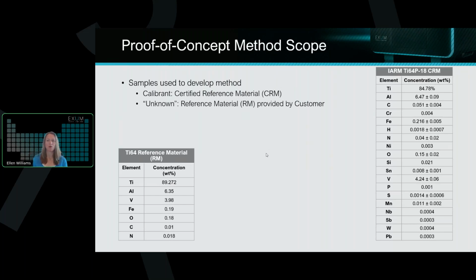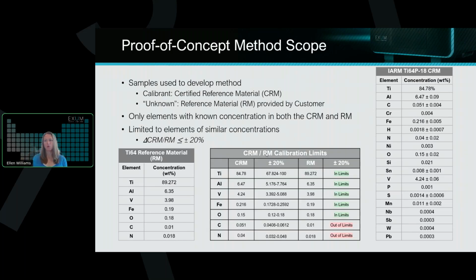So in this case, we have what you see on the left, which is a Ti-64 reference material we received from a customer that had sent this out to one lab and gotten one number for the elements of interest that you see here. So it's important to point out that for this method scope, we are limited to the elements that have been quantified in our reference material.